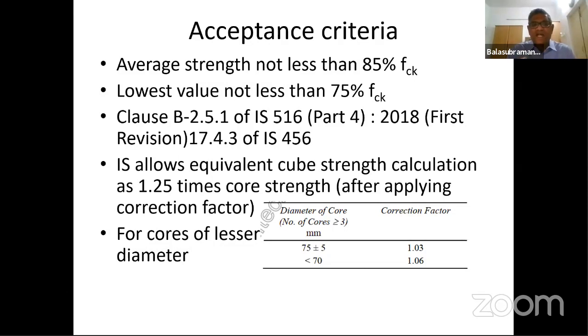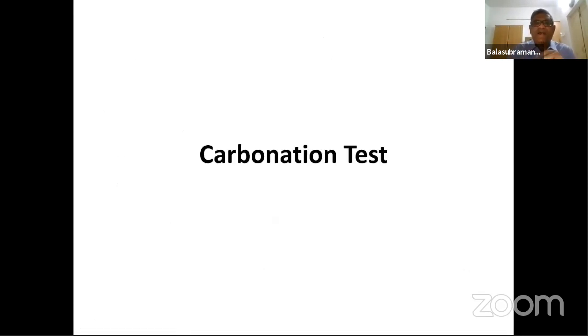And when we go for a lesser diameter core, apply the correction factor as given in IS 516 Part 4. This is a new one. Whatever you are getting, multiply by 1.25 to get the equivalent cube compressive strength. Then take the average and check that the average strength is not less than 85% of the fck, and the individual core is not less than 75% of the fck. So this is how we get the acceptance criteria.